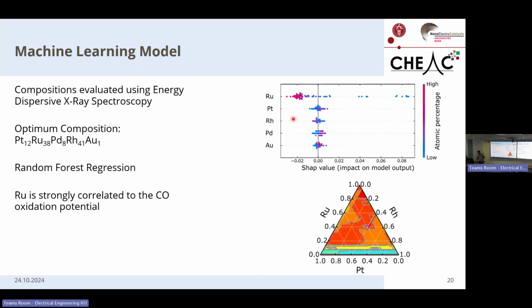The way to read this figure is to look at the spread of the SHAP values. So the larger the spread, the more important is this feature to the prediction. And then using the color scheme, we can see how this feature influences the prediction. So for this specific experiment, we see that ruthenium is the key element that drives the prediction of the model. And large amounts of ruthenium correspond to an increase in activity, whereas little amounts of ruthenium correspond to a decrease in activity.